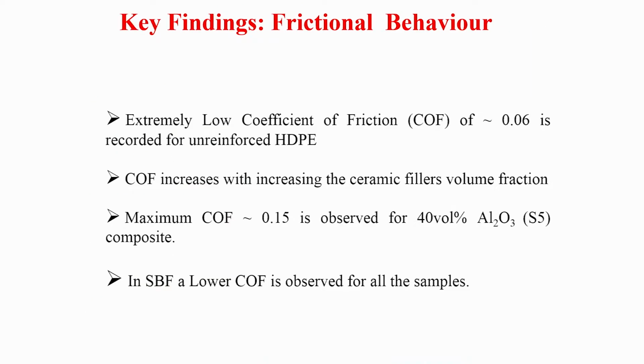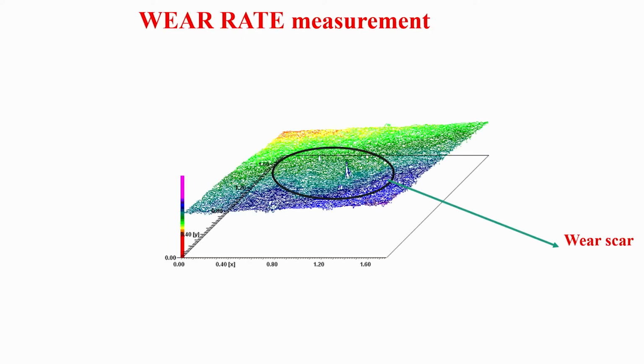Okay, so now these are the key findings. Certainly the coefficient of friction increases with the ceramic fillers, and the maximum coefficient of friction is 0.15, and in SBF, lower COF is observed for all the samples.